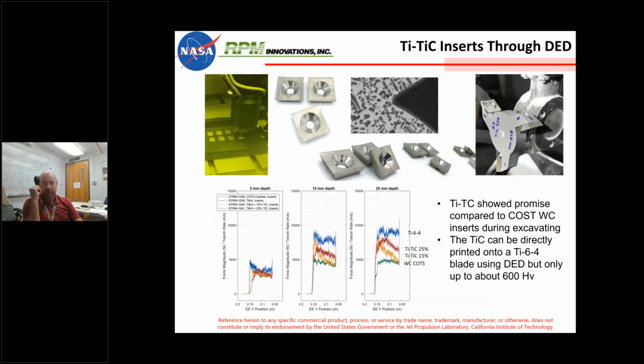So one of the things we demonstrated is we made cutting tool inserts out of these Ti carbide parts, and then we did the same experiments, cutting performance using these inserts, to demonstrate that we could actually develop Ti carbide metal matrix composites that have pretty excellent cutting performance compared to tungsten carbide, which was really surprising to us.